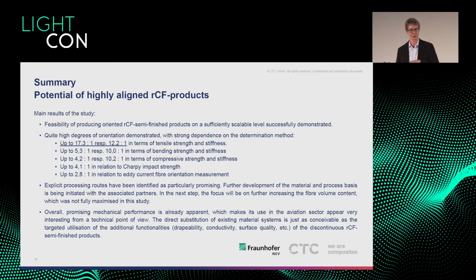MDCD, machine direction, cross direction, so how many fibers are in this direction versus this direction. And we found that this is actually quite a bad measure, because machine direction, cross direction gives you a very, very small indication of the performance, but not the real final values. And this is maybe something we should keep in mind when we brag about highly oriented rCF materials, because they are very different measures.